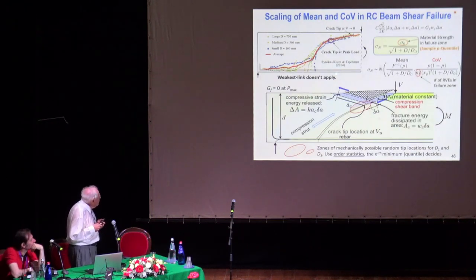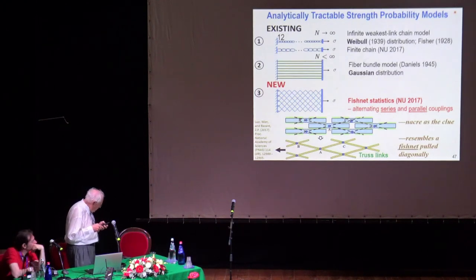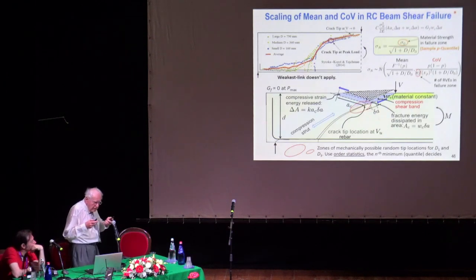Let me jump back briefly to what I already showed, this diagonal shear failure. This is the mechanism, with zero fracture energy because of crack-parallel compression. These bands of spreading of failure linearly expel this. That can be analyzed, and this goes to this formula, which can of course be extended to calculation of the coefficient of variation as it varies. I will not go into details of this formula, but it was shown that at first the coefficient of variation decreases, which would be true of ductile failure, a Gaussian distribution, but then it stabilizes as a constant, which is characteristic of the Weibull distribution.